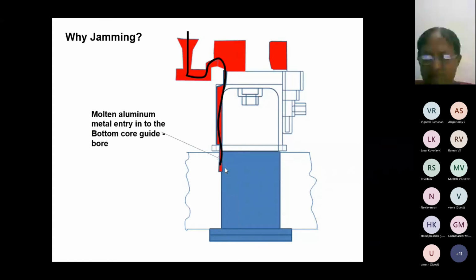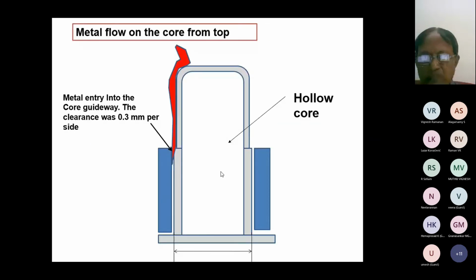So what we made is how to solve this problem on this one. This is a hollow core and this is the shank. Normally, the shank diameter is only 2 mm bigger than the core bottommost diameter of the casting. And this 0.3 mm is mandatory for free movement. If it is not there, the core will not drop because the core temperature will go up to 270 degrees by the time this expands and goes in that. And if it is 0.1, again the core jams. It's a very critical position, how to sort it out.